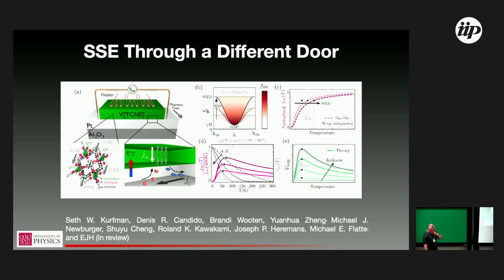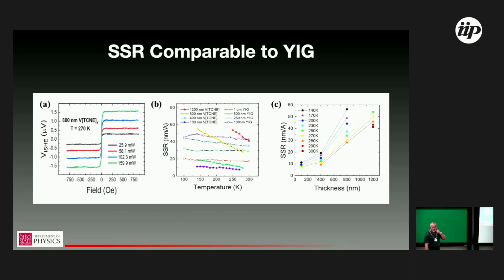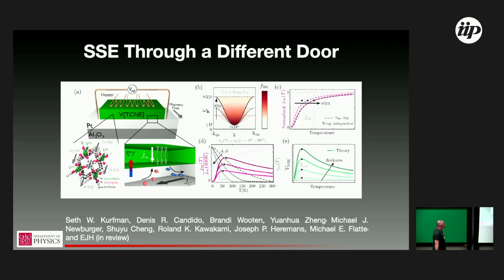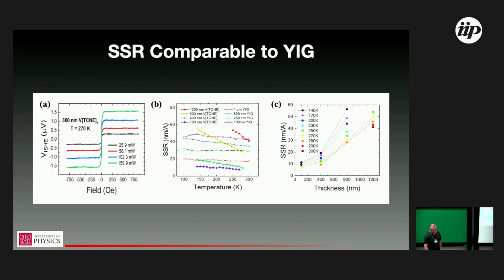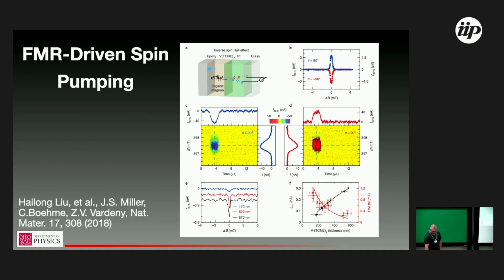Similar to the Prussian blue, we also have been able to measure the spin Seebeck effect in VTCNE, and this is work that Dennis Candido led the theoretical development of. So he's around to ask all the hard questions of. And I'll just say that again, because of this extremely low damping, VTCNE gives similar performance metrics to YIG. The longer story, which I don't have time for, is that this combination of strong exchange and low MS puts us in an odd regime for optimizing the spin Seebeck effect, where normally you would want a large magnetization. It has a very small magnetization, but that couples to the low damping in ways that are interesting in tuning the magnon band structure to effectively circle around and end up with numbers that are comparable to YIG. Similar for FMR-driven spin pumping.